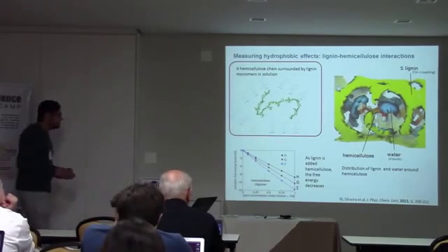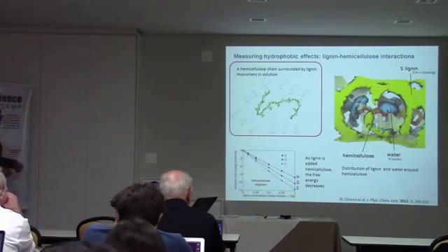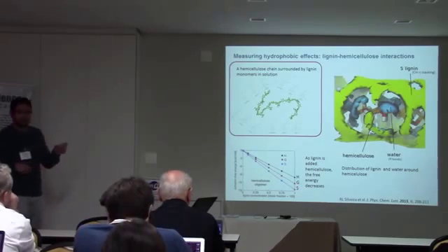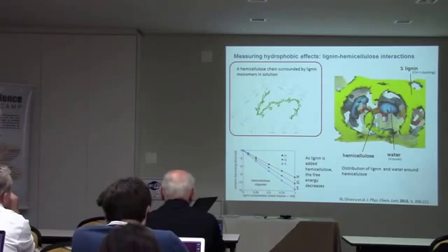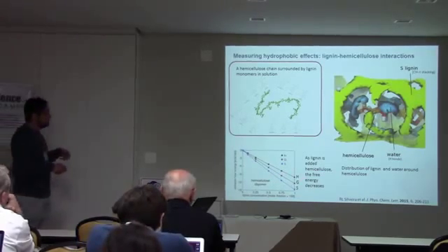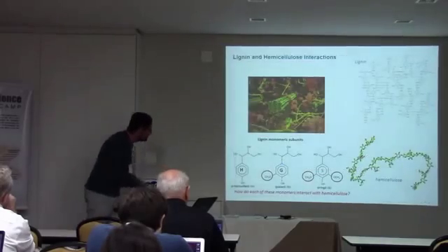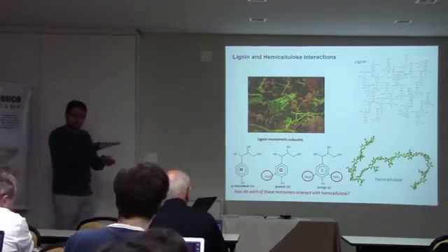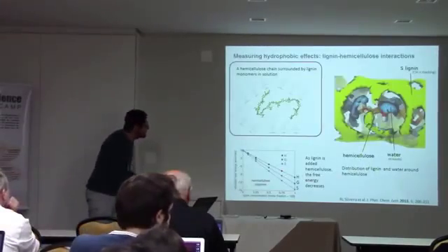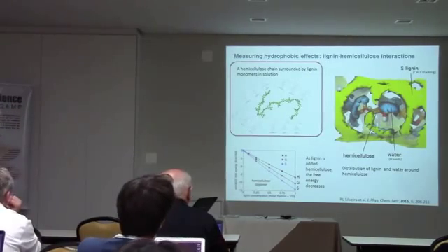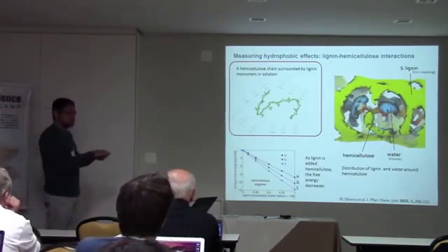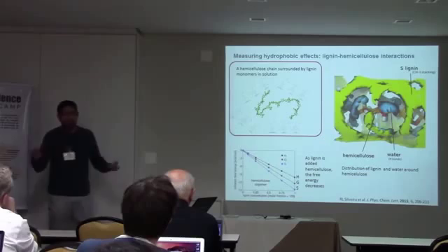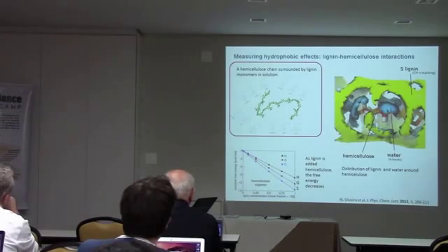So that's why we have this thermodynamic behavior, and it also explains why the methoxy groups attached to the aromatic ring stabilize more than the H lignin, because as we have these methoxy groups here, we have actually a larger surface area of these monomers. So the surface area can cover more effectively the hydrophobic face of hemicellulose and prevent water from reaching the forbidden regions of the hemicellulose. That's why we have